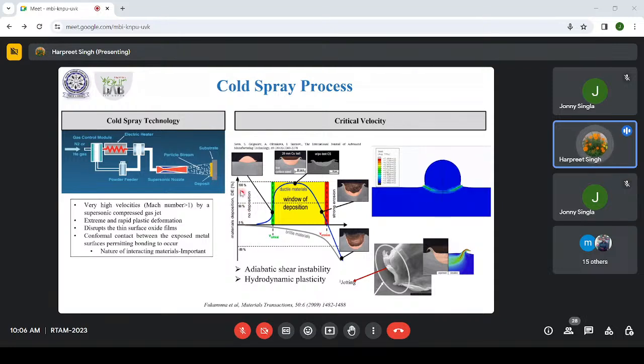So material deposition is on this y-axis, and on the x-axis we have velocity. Now, velocity and deposition efficiency have a strong correlation here. You can see that at certain velocities, you will have no deposition at all. In this scenario, the particles will rebound. But there will be some critical velocity, V critical, here. After that, the deposition will start.